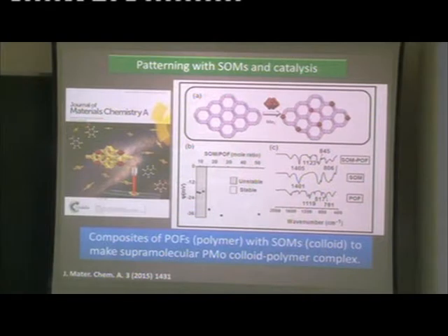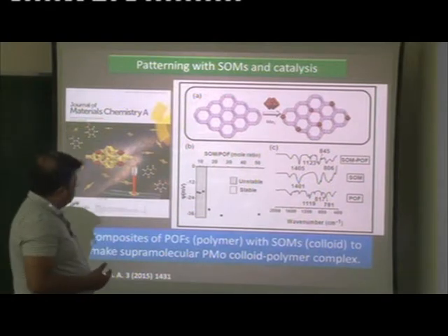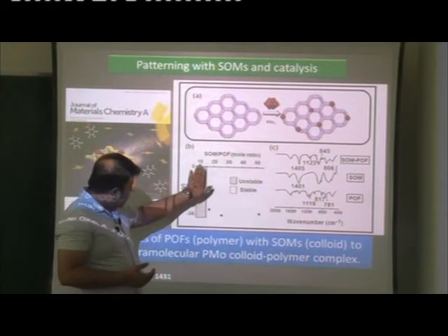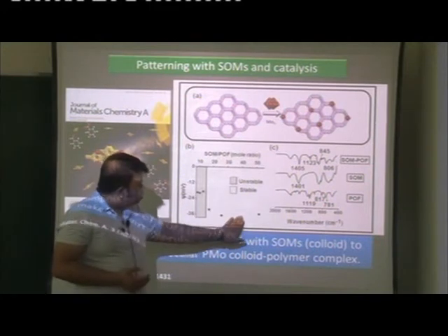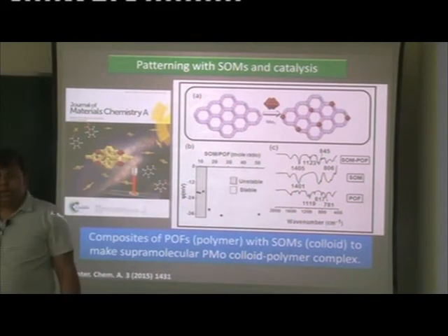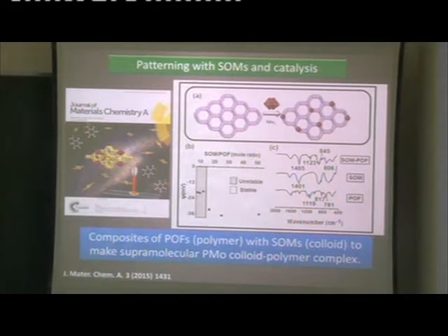which in turn we could monitor from the zeta potential measurements. It shows an unstable regime, and then it goes to a stable regime and stays there. Now from the zeta potential measurement, when you have the stabilization, usually you have stabilization in the order of around 20 to 30 millivolts.